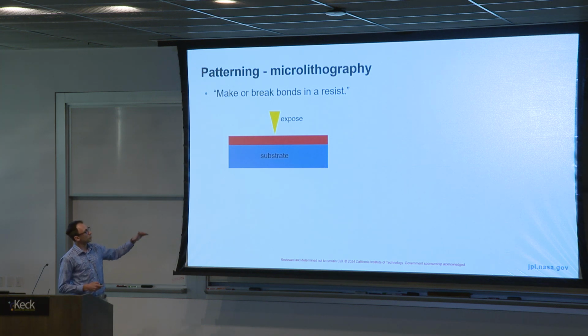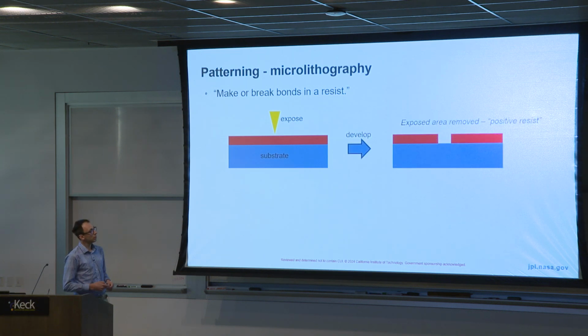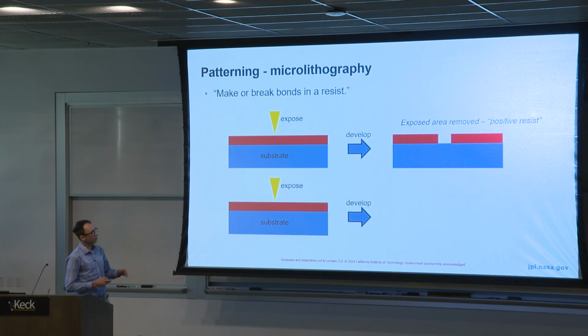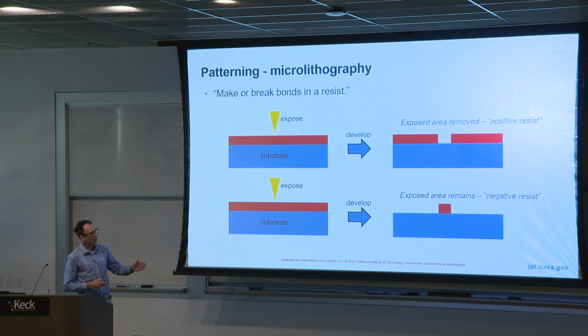So it would look something like this. You have your substrate, you spin coat your resist, you expose it. Let me get back to what that means in just a second. You would put this into a developer, and if your exposed area is removed, that's called a positive tone photoresist, or resist, I should say. I try to avoid saying photoresist because of e-beam, but I often slip. I mean resist. You can also expose the resist, develop, and your exposed area remains. That's a negative tone resist.